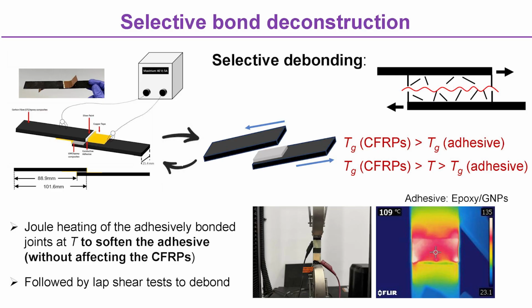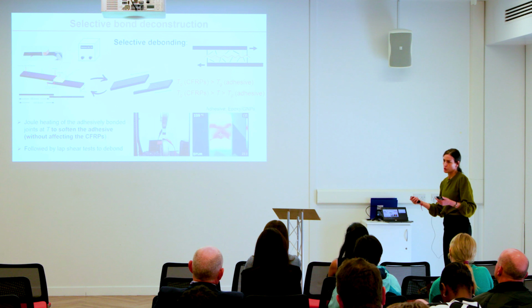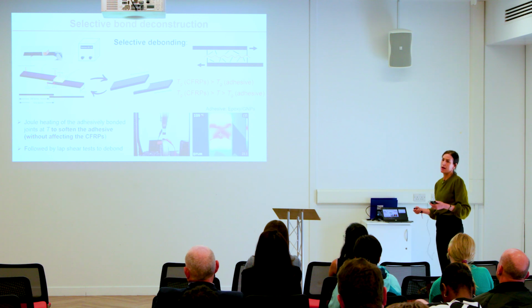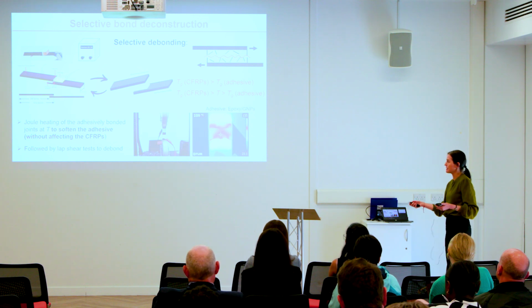So finally, the third question we wanted to find an answer to is: is selective debonding possible? In order to realize this idea, it is important that we strategically select the epoxy used to manufacture the composite and the epoxy used to formulate our adhesive. The Tg of the composite needs to be considerably higher than the Tg of the adhesive so that we can Joule heat the bonded joints up to a temperature in between them both, to make sure we are softening the adhesive for an easy deconstruction without altering or damaging the components or the composite.